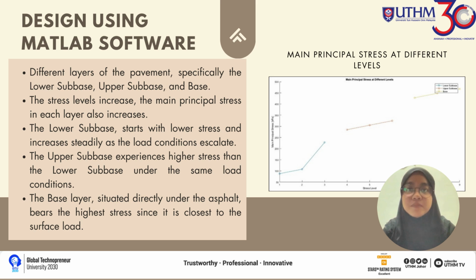Next, the upper subbase experiences higher stress than the lower subbase under the same load condition. The base layer situated directly under the asphalt bears the highest stress as it is closest to the surface load such as traffic. It must be the strongest layer to prevent pavement failure like cracking and rutting.